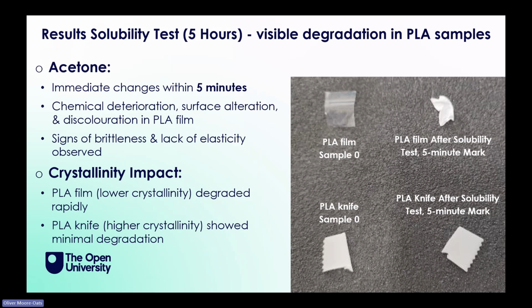So we did a solubility test of about 5 hours, and we see some visible degradation on our PLA samples, especially in acetone, which confirms our theory and solubility parameters. If you remember in the previous slide, 19.9 was PLA and 19.7 was acetone, so they're really close. As you can see, we have immediate change within 5 minutes. So we have a chemical degradation, alteration, and discoloration of the PLA film. So basically from clear it became white and then became brittle and stiff.